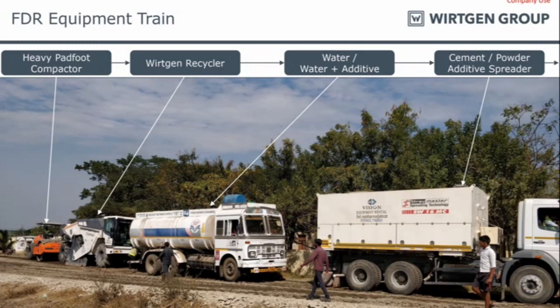The next equipment is this Wirtgen recycler. It is connected to a water tanker in the front. The recycler pushes the water tanker forward, and it sucks water as per your OMC, as per the required job site requirements. This machine is capable of pulverizing from a depth of 2 mm to a depth of 500 mm in a single pass. And as you saw in the animation, this is the mixing chamber. We have the milling drum inside this machine. It pulverizes the different layers of your pavement along with water as well as your pre-spread cement.